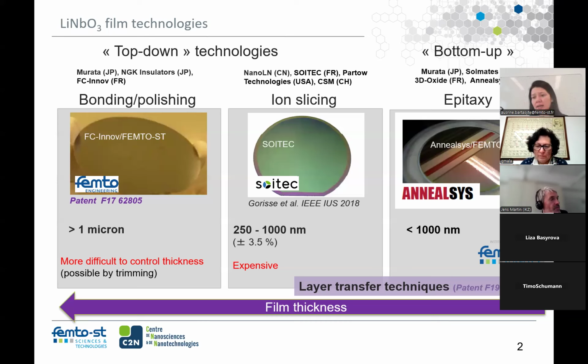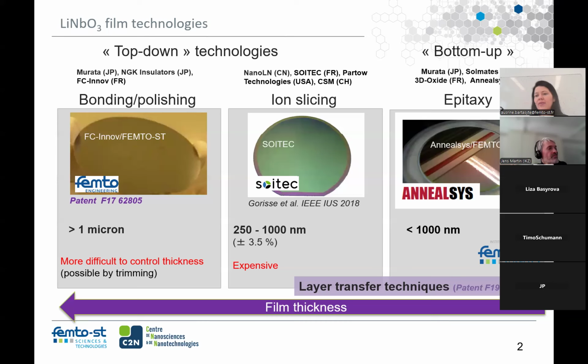And then in parallel, we have ion slicing, where you do implantation. Then you do bonding, and then cleavage by heating, and then you have annealing to recover the properties, because implantation damages the crystal, and then polishing to get back the quality of the surface. So in this case, you could reuse the initial wafer several times, but we have a lot of steps to produce a film. The film thickness will go from, let's say, 250 nanometers to 1 micron, maybe 900 nanometers. It will be limited by implantation depth, so we cannot make thick films by this method.